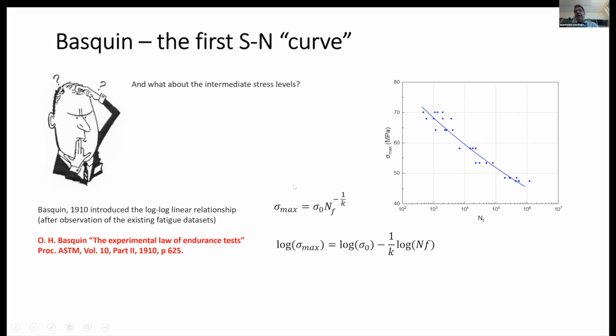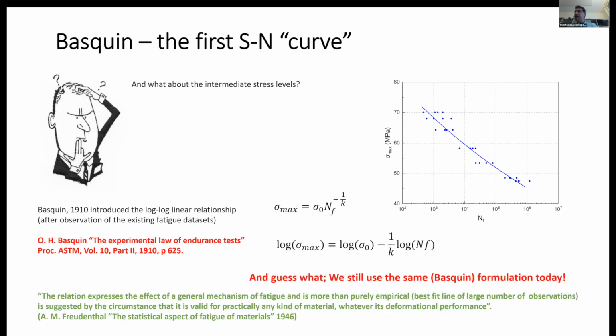And then in 1910, so 100 years before today, another engineer, Basquin, introduced the experimental law of endurance tests, as they called it, and it was reported in the proceedings of the ASTM in 1910. It is actually the logarithmic or log SN curve. It's an equation saying that if we plot the maximum stress or the stress parameter against the number of cycles on a double logarithmic scale, then it is a line that can simulate the behavior of this material. And guess what?